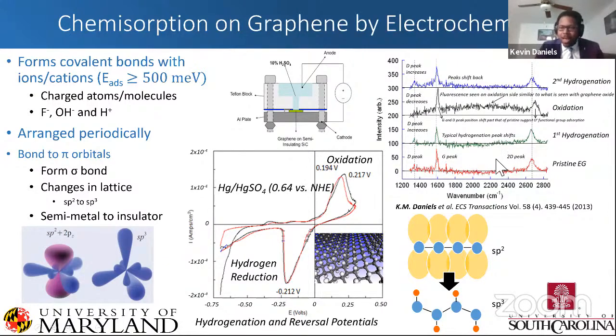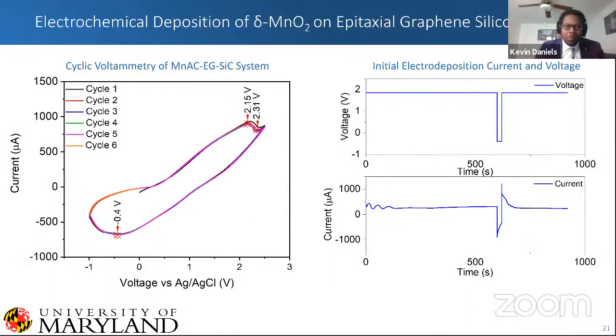And sure enough, you can go from pristine graphene, this is again the Raman spectrum, putting hydrogen on, you see this increase in this D peak or this disorder peak, which is also significant because it increases with increasing sp3 content. And then we drove the hydrogen off thinking that, okay, we'll go back to pristine graphene, but it didn't. It actually oxidized. And you can clearly see this through this fluorescence here. And so we were like, okay, well, if we can seed the surface with oxygen, we could clearly just put manganese on the surface. And so that's exactly what we did.